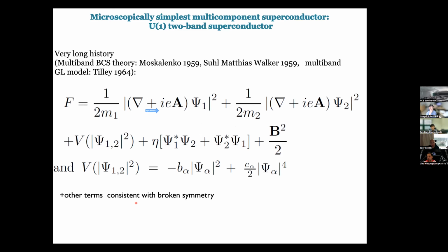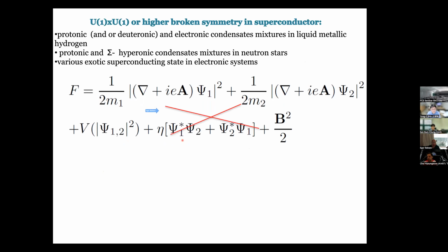And like most of the materials of current interest, they are multi-band superconductors. You have multiple electronic bands, and in each band you can form a superconducting gap. And then the simplest possible generalization of the Ginzburg-Landau equation is to a superconductor with two order parameters, two complex fields. And that was known for more than half a century. And then you may even have multiple fields, but still only a single broken symmetry if you have Josephson coupling between components.